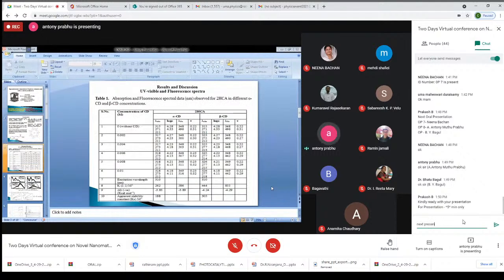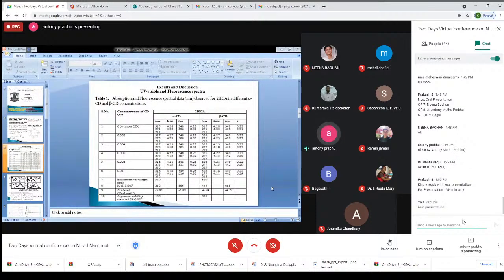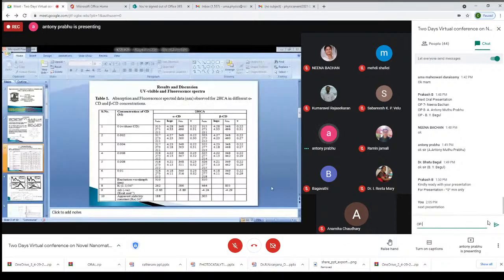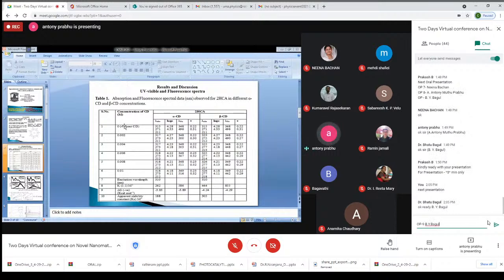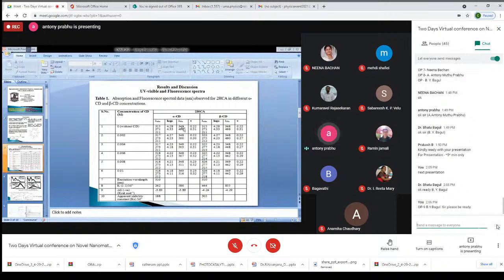Then directly go to the results and discussion part. So the UV-visible and fluorescence spectral data are shown in the table. The absorption maxima of 2-hydroxycinnamic acid were observed at 350 nanometer, 271 and another at 211 nanometer. And emission maxima were observed as 2 peaks at 348 and 496 nanometer. This table shows that as the concentration of CD increased, the absorption decreased, with a redshift in the absorption maximum, and the fluorescence emission was also redshifted with increasing concentration of CD.